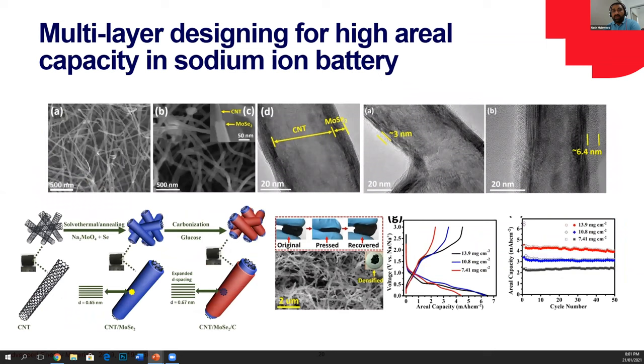There is another example, a similar example, but that was about particles. If we have 2D materials, how can we confine them? For the 2D materials, we put a conductive matrix inside, then we coat the material on top of it, and then we protect it with carbon. We found that if we do this in a sponge, they are even more active towards a higher volumetric capacity, because volumetric capacity is also an issue.